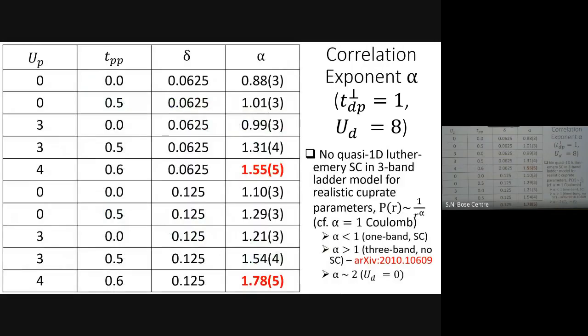So that's the result. This is different doping. And this is, of course, not realistic. You can get alpha less than 1, but for the realistic set of parameters, alpha becomes greater than 1. So we said that there is no quasi-one-dimensional Luther-Emery superconductivity. This is not on arXiv, this appeared in Phys. Lett. There was intense objection to this paper because they said, oh, DMRG papers are not interesting anymore. Not true. As I said, DMRG papers are still appearing, and I'll come to that. But essentially, once you put in the oxygens, the pairing disappears.